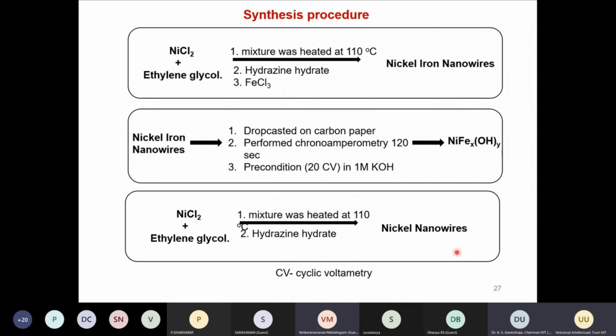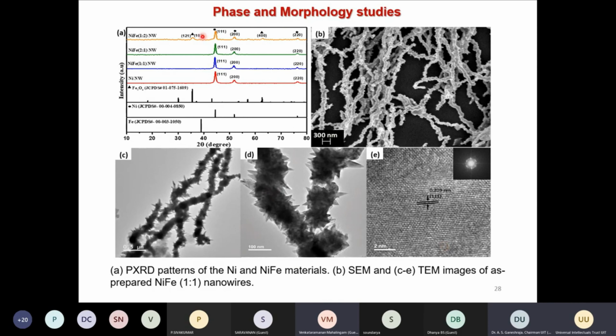For comparison, we have made only the nickel wires with the same experimental procedure. What we see is that the XRD pattern clearly confirms the presence of iron nickel nanowires. With the increase in the iron content, for example, if you take an iron content of 1:2, we start to see the peaks corresponding to iron hydroxide. So we felt 1:1 is the sample which shows a pure NiFe phase, and we optimized it and used it for further characterization.